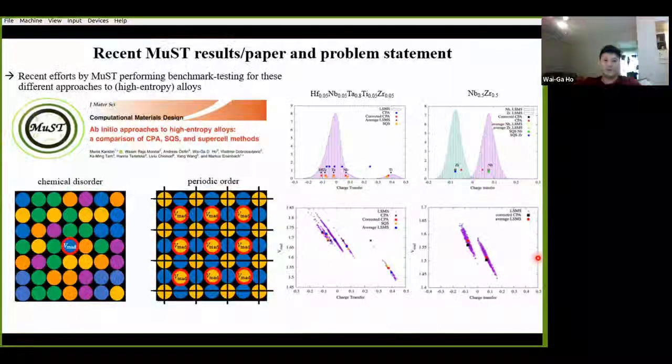And so this so-called charge transfer was actually the second concept that I wanted to establish for the x-axis of these plots, and for which I've done in the periodic case. But now for the disordered problem, the atomic environments are random. And that means that I now have to have some statistics for both the Madelung fields and the charge transfer, right? Because even if I'm looking at a particular species, this green atom's environment is different than that green atom's environment. And therefore, they're going to see a different number of charges transferring and different electrostatic Madelung fields, according to the underlying disorder statistics.